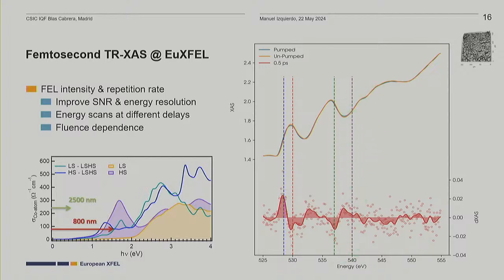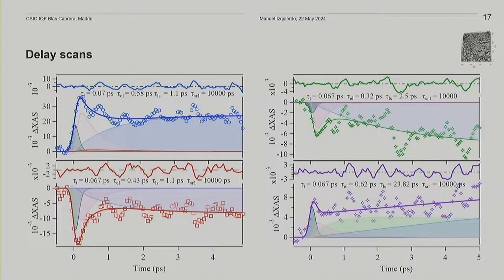cobalt 4SP band. So in this case, we wanted to give a twist, and then we decided to, instead of using 800 nanometers, do a sub-gap excitation of the system. And so when we analyze the data, because we have high pulse energy and high repetition rate, your delay scans are now much richer in structure, and you are able to see the same components that we saw before, but we also see some oscillations in the residual. That is related to the fact that we are exciting some low energy modes.